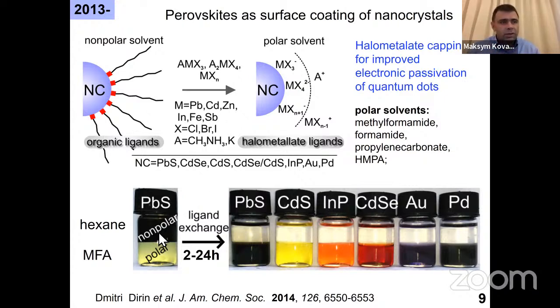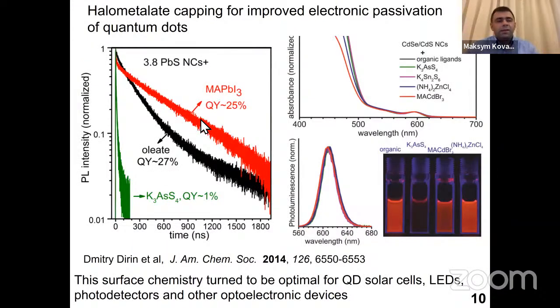And that you see from the dispersion of these nanocrystals, they migrate from the apolar phase into a polar phase upon this ligand exchange. And what was extremely important back then is to observe that such an exchange can preserve or even improve the electronic state of the surface. So somehow it turned to be very beneficial to have halides at the surface as compared to chalcogenides, for example. And so that you see from the retention of high quantum efficiency for the luminescence in the visible and in the infrared spectral range and so forth.